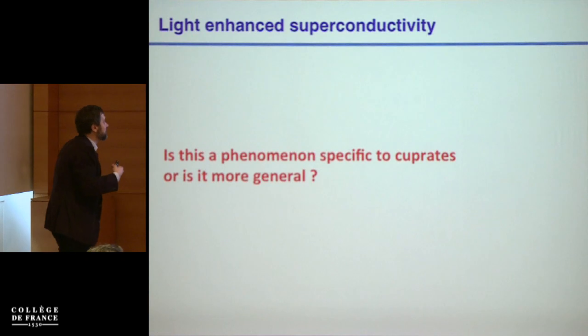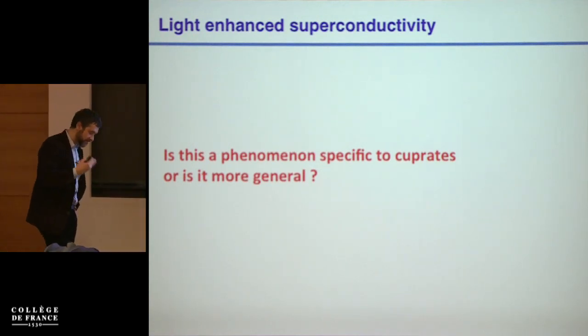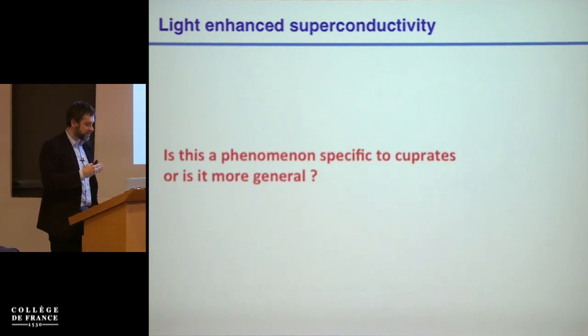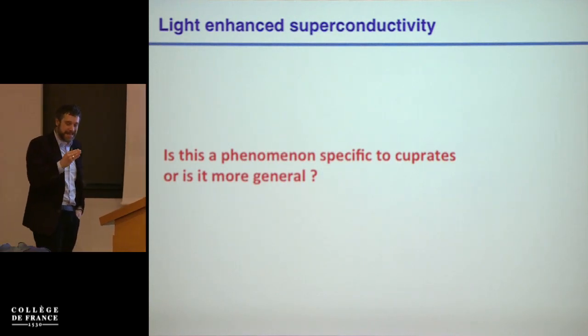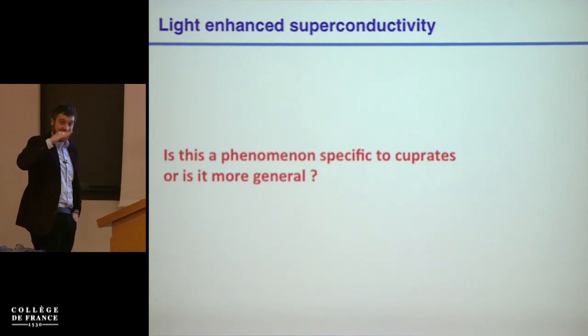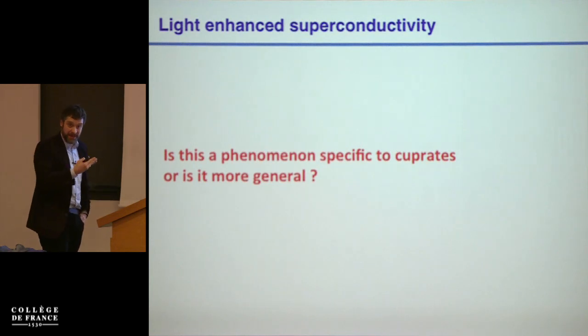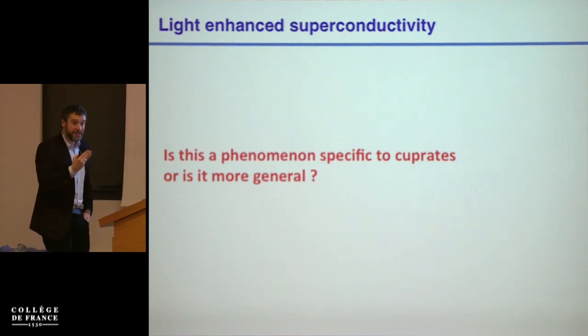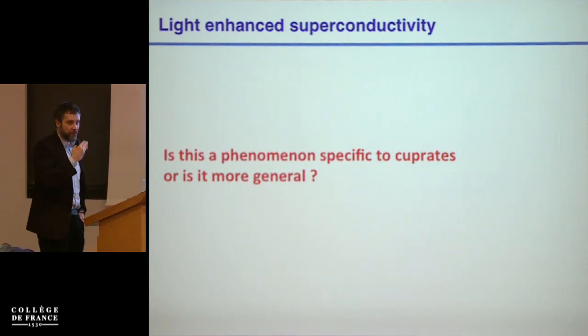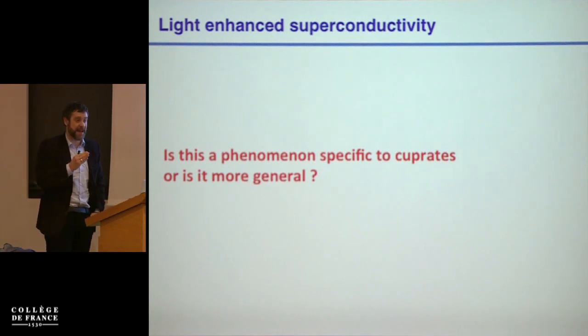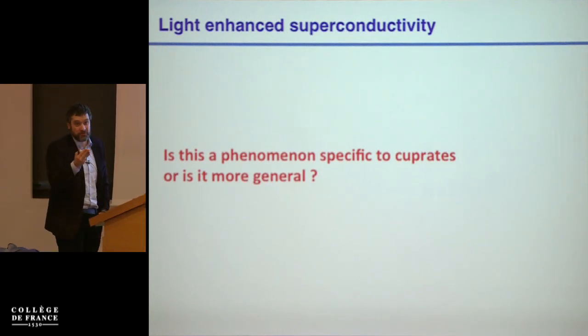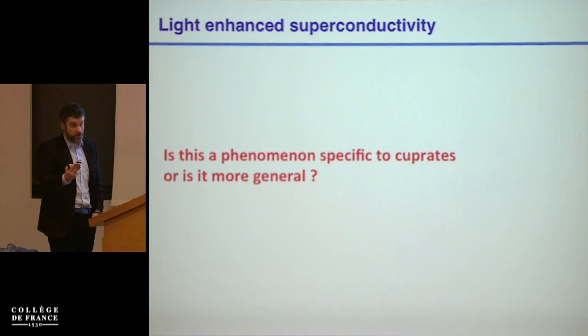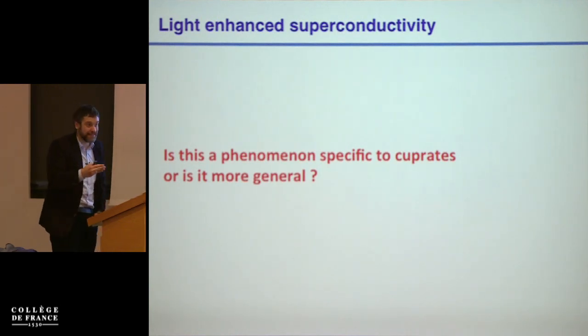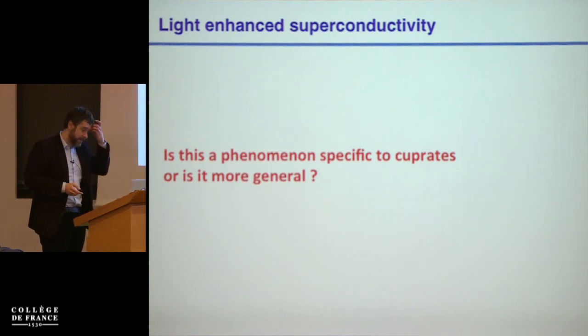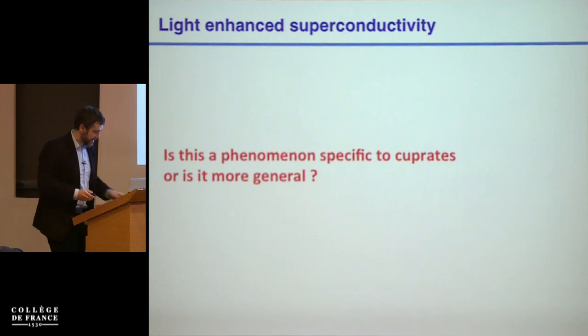Is this phenomenon specific to the cuprates, or is it more general? I mean, what I've discussed, of course, are cuprates, which not only are very difficult to understand, but are also materials in which there's many things that are special, including the fact that the interlayer tunneling, although it might not be the driving mechanism, as some have suggested at some stage, is nevertheless related to the whole business. So lots of people, normally theorists, ask me, can't you take a normal superconductor and do the same? Of course, if you take a normal superconductor like aluminum or mercury, these materials tend either not to have optical phonons, and therefore not to be easily modulated with light, or not to be simply conducive to experiments like this.